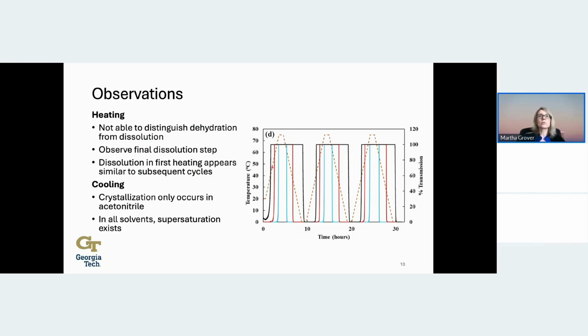As I already mentioned, the dissolution times look pretty similar in all 3 cycles, even though we have them start with the monohydrate here. Perhaps then we have the dehydrated form 1A that's dissolving and that we're observing here. But we really don't see obvious differences in the 2nd and 3rd cycle. Observations for cooling are that crystallization was only observed in acetonitrile, although in all of the solvents we did have supersaturation upon cooling, but probably we just didn't wait long enough to have crystallization in the other solvents.